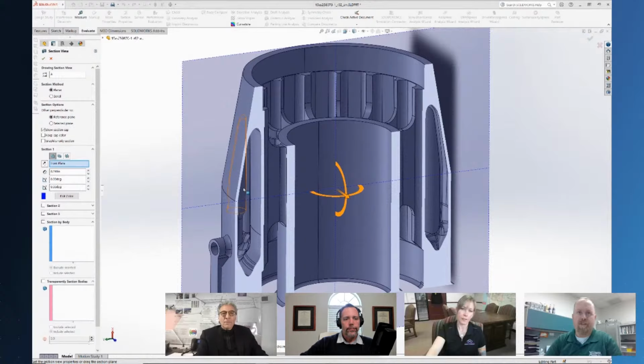I've had other applications with various corrosive environments where internal features were a concern. And so when you're coating this, you're coating the internal channels as well. Once we printed the part and then had it heat treated, and after finish machining, which we also do in house, then we do the eTCP coating on this one. And that'll coat every surface of the part, not just the visible and external surfaces.